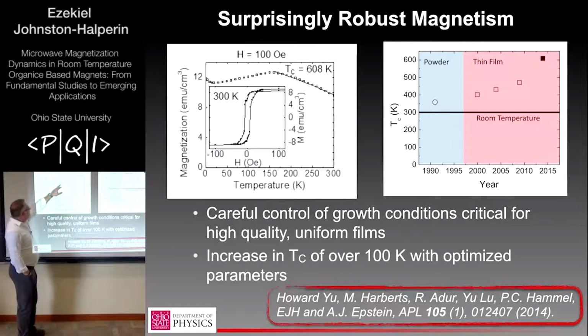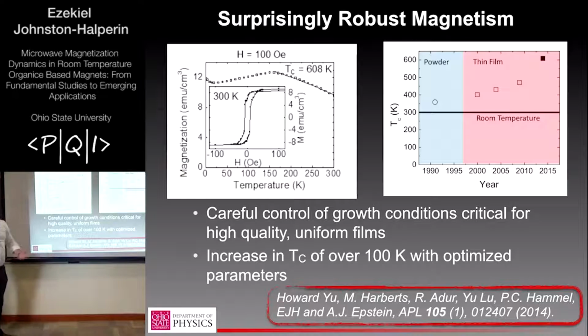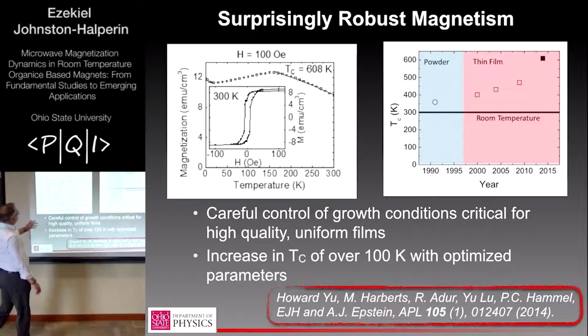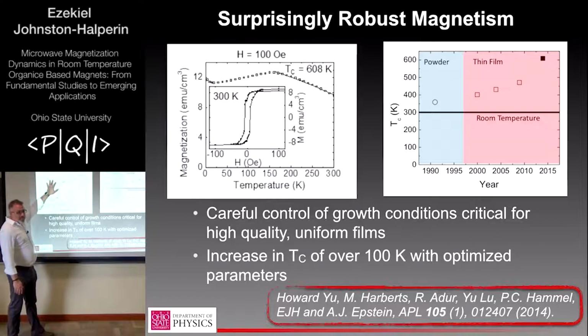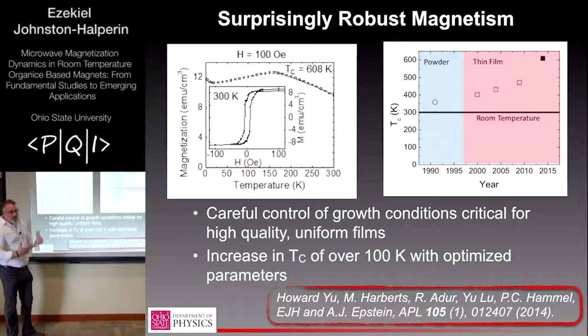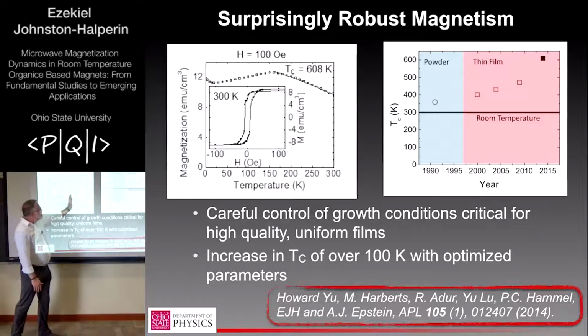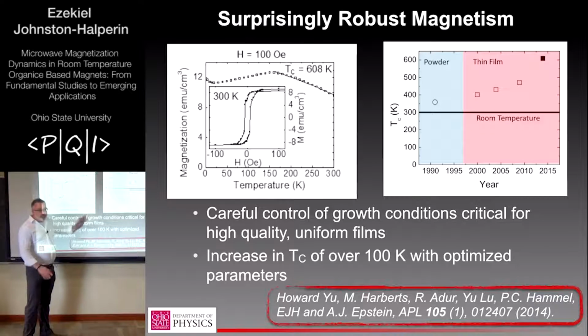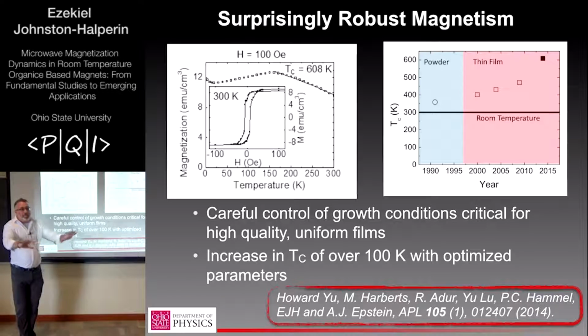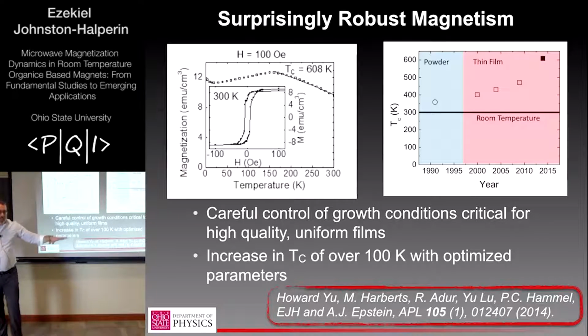And I think that's connected to this reentrant phase here, where it becomes more disordered at low temperature, more antiferromagnetic. I think this is actually related to carrier freeze-out, coming back to really interesting and outstanding questions about how transport works here. Because I think that the presence at high temperature of more delocalized carriers helps to stabilize and homogenize the magnetic phase. It goes up again.